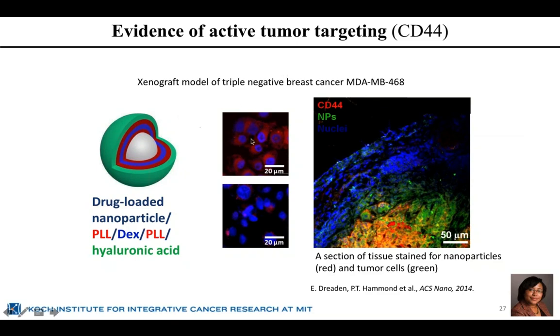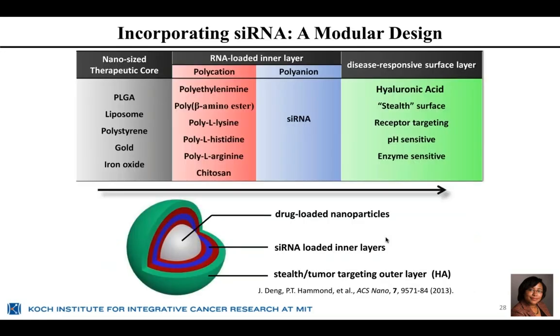So here we can see some cells which have taken up our nanoparticle, which is shown in red fluorescence, and the case where we essentially titrate away those interactions with excess hyaluronic acid and eliminate that uptake. We can also see a tumor slice in which we stain for CD44, and we can see the nanoparticles and the overlap here in the tumor section in yellow. We get a very high accumulation here. This gives us three ways of targeting the tumor: by size, by tumor hypoxia, thanks to these layer by layers and their tendency to be responsive to pH, and by cell receptor through the choice of that outer layer.